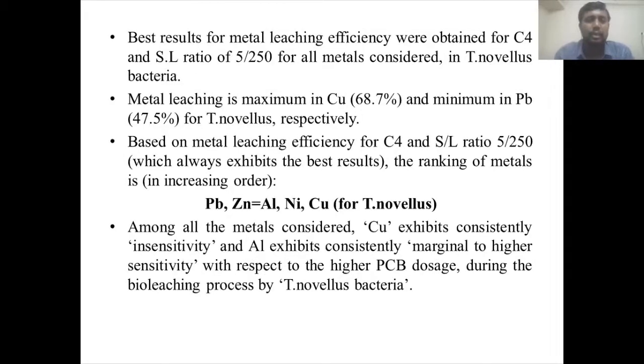Yeah, the best results based on the metal leaching efficiency for C4 and solid-liquid ratio 5 by 250 is, we have ranked the metal leaching in increasing order: lead, zinc, and aluminium are having the same equivalency. And next to that is nickel, and copper is at a higher level for T. novellus.